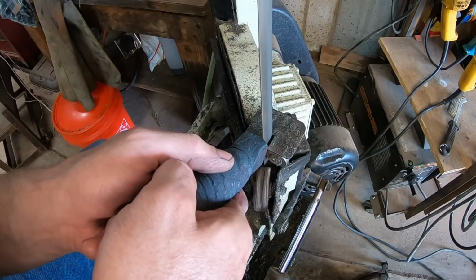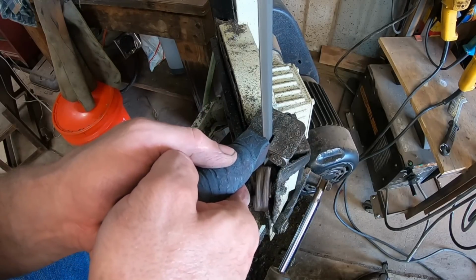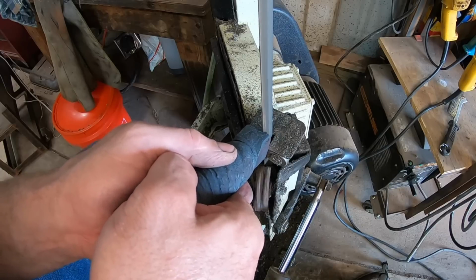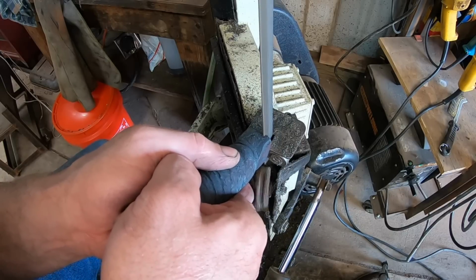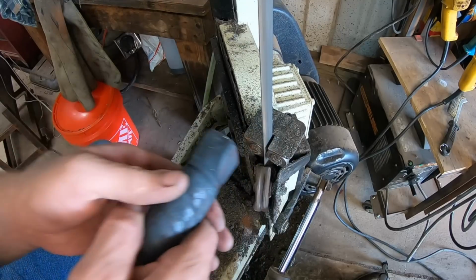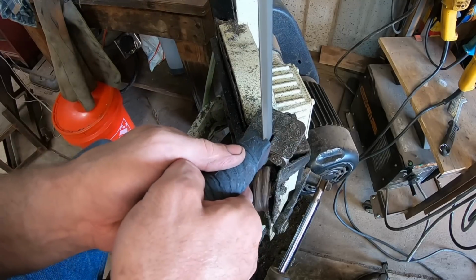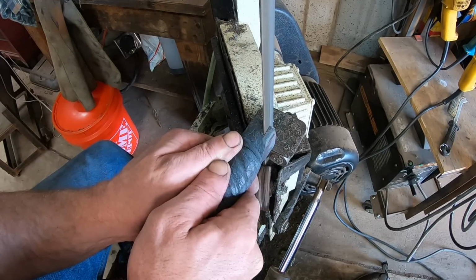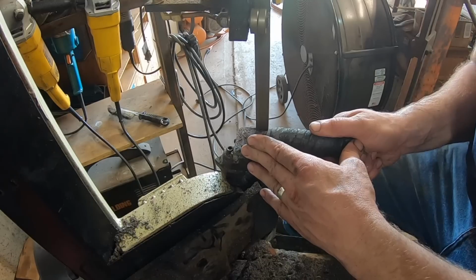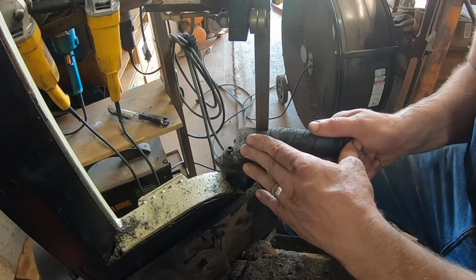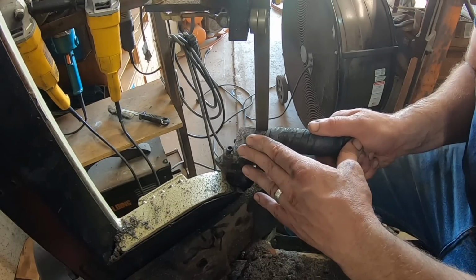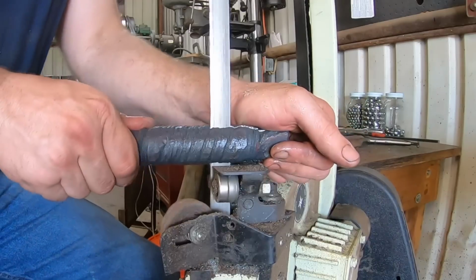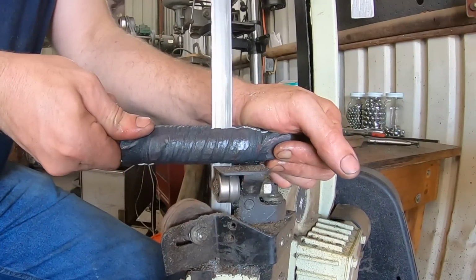So pulling it out of the kiln there, and that was in annealing cycle so that it will be soft enough to now cut the billet on the bandsaw. This bandsaw is not really set up for this type of cutting, so getting the cut started was a little challenging, but once that was there, we could just slice off some slabs on either side.